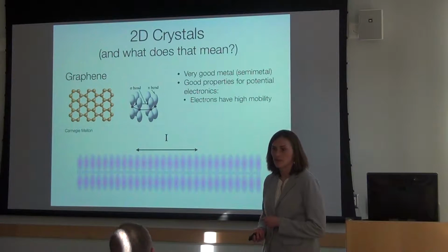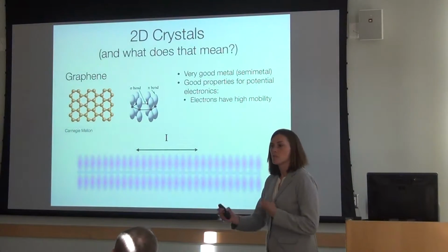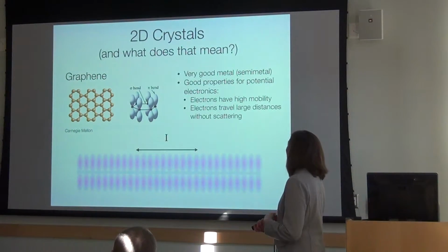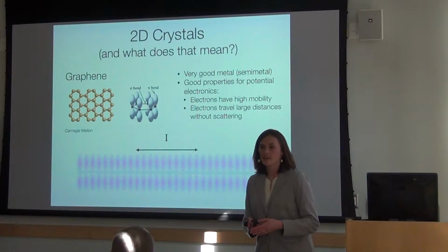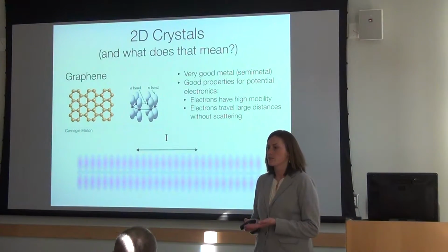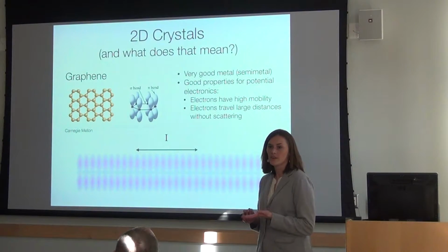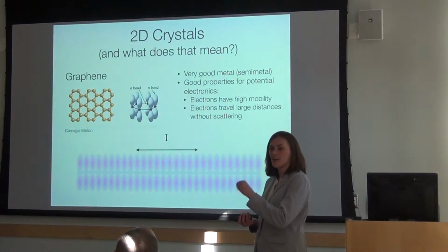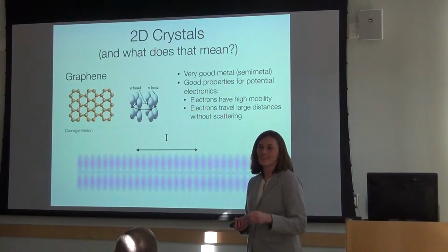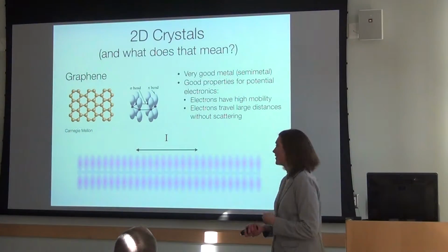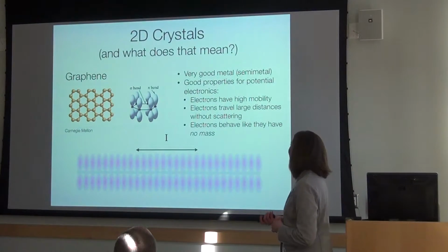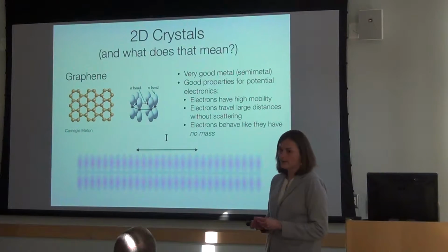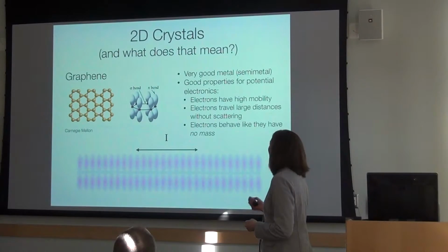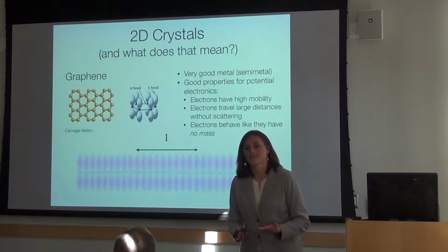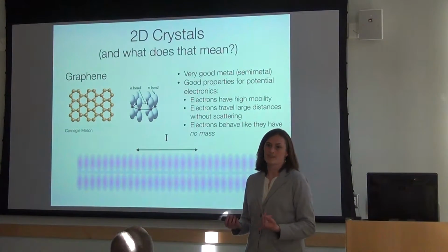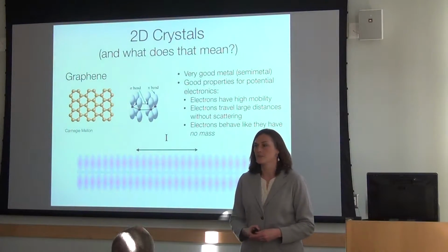Electrons in graphene have a high mobility, so when you push them with an electric field, they move very easily. And they can travel really large distances without scattering. So you can actually do ballistic transport experiments at room temperature with graphene. That means you push an electron on one electrode, and microns later, it arrives without scattering. And also because of the unique band structure of graphene, which I'm not going to get into, the electrons in graphene behave like they have no mass. So you can do relativistic type experiments with electrons in graphene as well.